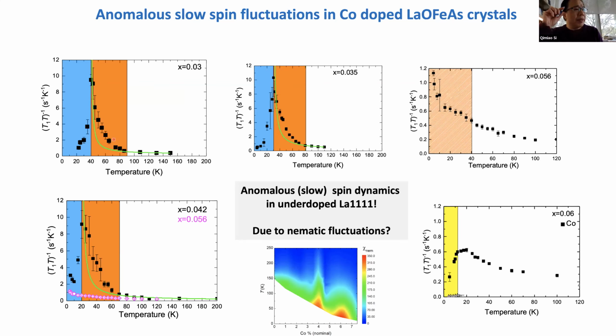Just to follow up: in 122, one could maybe avoid this glassy-like behavior by looking at phosphorus doping as opposed to cobalt or nickel doping. I was wondering whether, from a materials perspective, one could also look at phosphorus doping in 1111. Yes, of course. The big challenge is to get fluorine doping in there, because fluorine is out-of-plane doping. Just looking at resistivity and the phase diagram, there's a tremendous difference. The maximum Tc you get in the cobalt-doped samples is about 11 Kelvin. If you take the same samples with fluorine doping, you get 30 Kelvin. These systems are much cleaner, but it's even more challenging to get these crystals. We have been working on that for years, and so far we are not able to get the phase diagram for the fluorine-doped single crystals in a way that I can present it. Maybe I can do it next year, but at the moment I'm not able to.